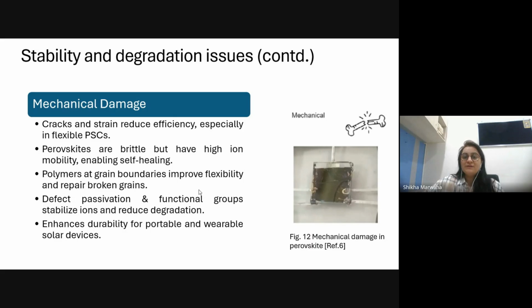Next is mechanical damage. Most of you know that we work on a glass substrate when we work on perovskite solar cells. Even if there is a crack or a strain, that degrades our device performance. It is there in silicon also; silicon is quite brittle, and that will also degrade performance. The same is the case here. They are prone to mechanical damage, in which a crack or a strain can reduce the efficiency of our perovskite. They are brittle, but they have high mobility, which enables self-healing.